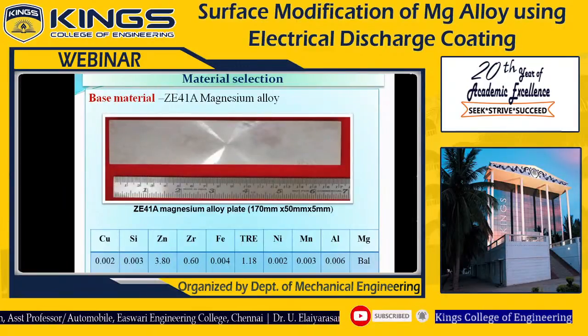Here the chemical composition of this ZE41A magnesium alloy has been given. Zinc is 3.80%. There are several elements: copper, silicon, zinc, zirconium, iron, TRE meaning total rare earth, nickel, manganese, aluminum and magnesium. Among the different compositions, which are higher? Zinc is 3.80, and the other is rare earth at 1.18. So this material is ZE41A: 3.80 rounded is 4, and rare earth 1.18 rounded is 1. So that is the 4 and 1 in ZE41A magnesium alloy. You can understand; similarly, the previously discussed materials are also denoted like that.